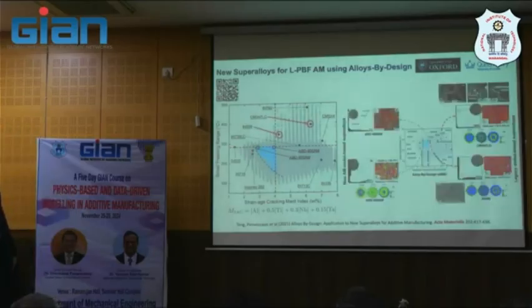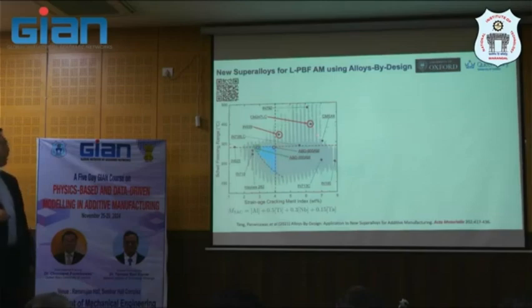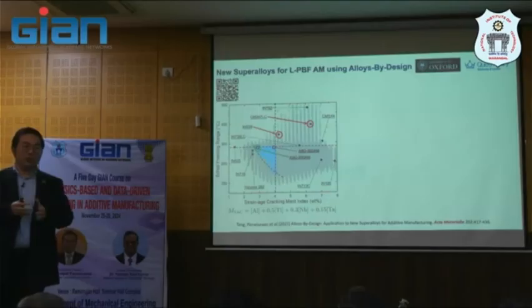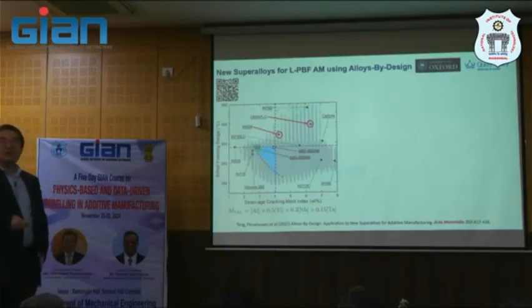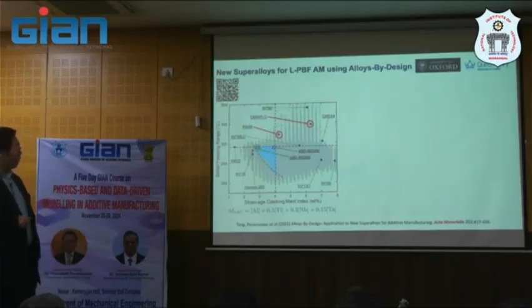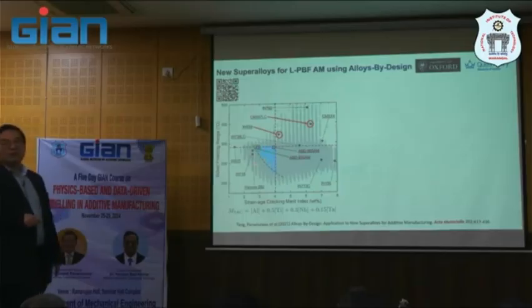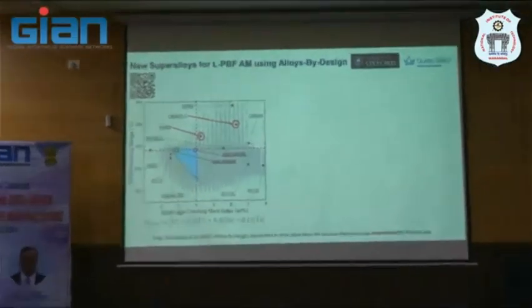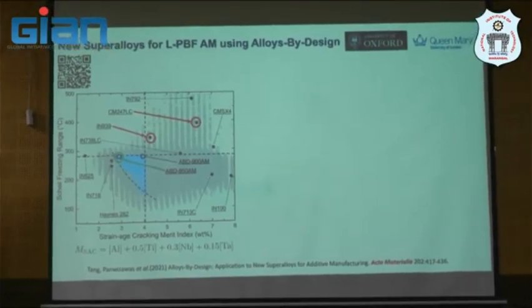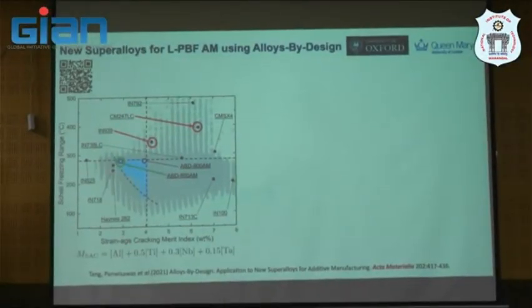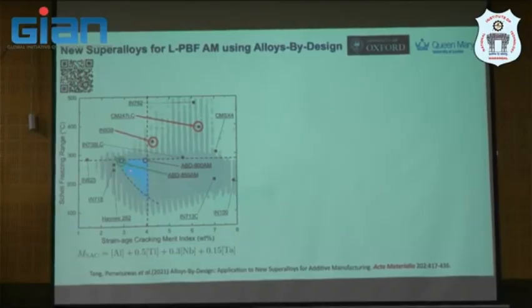What you will get is about 10 million compositions here in the range of acceptable nickel-based superalloy, not too much. Because you have a range for each composition already for superalloy, you can get what we call the design space here that you can look at in the gray dots, and you identify the range that you believe is a working condition for additive manufacturing, and then they draw this line and get the window of the freezing range. As I said before, the freezing range should not be 400 like CM247. I mean, this is also 350 as well. We set it below about 300 or 280 something for both compositions, and then we select these two as a function of freezing range, and it's actually not too high in the cracking index.